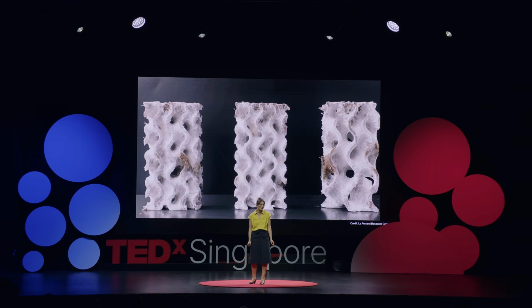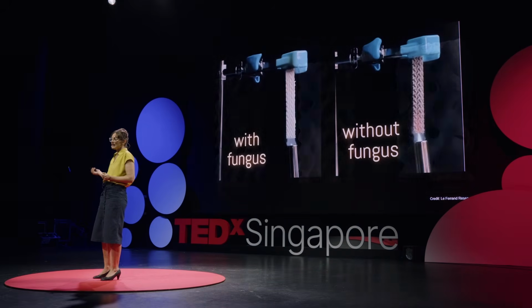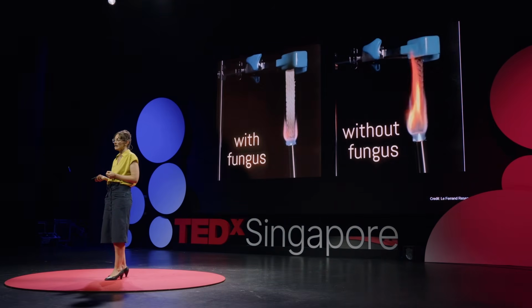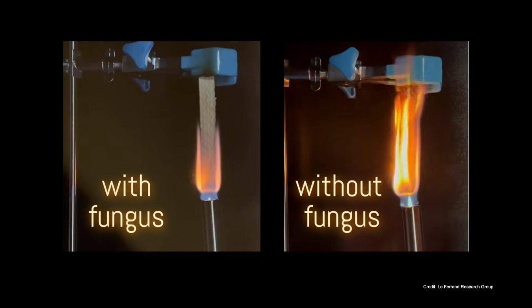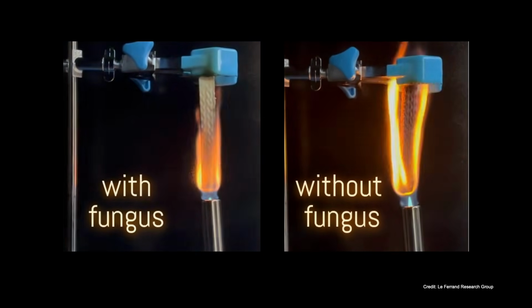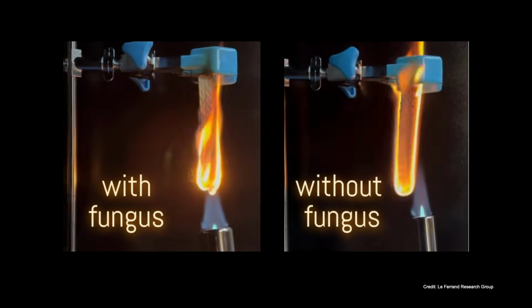This hybridization between the bioplastic and the fungus allows to combine the mechanical properties from the bioplastic, strength, stiffness, toughness, with the functional properties from the fungus, water resistance, temperature resistance, and even fire resistance. See how those two samples behave differently. The bioplastic scaffold without the fungus has a much bigger flame than the bioscaffold with the fungus. And that material here is entirely biodegradable.